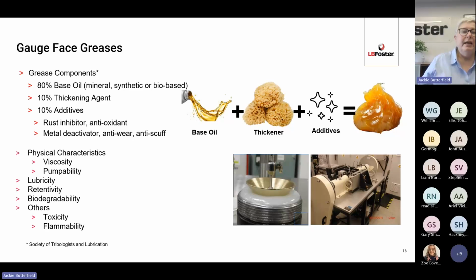These additives can be various formulations for corrosion resistance, antioxidants, deactivators, anti-wear additions, anti-scuff additives as well. So we're looking for a number of key physical characteristics for these greases to survive in the wheel rail interface. First is viscosity. You need a specific viscosity to perform. Ideally, they need to have a stable viscosity range over a range of temperatures, so that in summer, it will provide the same performance as it will in the depths of winter.